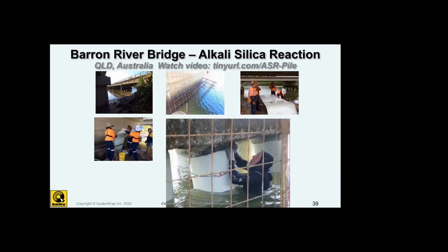This was a unique project that we did about 10 years ago in Australia. The piles on this bridge were suffering from alkali silica reaction. This ASR is something that some people refer to as a cancer of the concrete, and it causes expansion of the concrete. Prior to our repair, they had used 2 different systems, but each of those, after 2-3 years, the jackets would bust because they couldn't resist the expansion force of those columns. So here, we are repairing this.